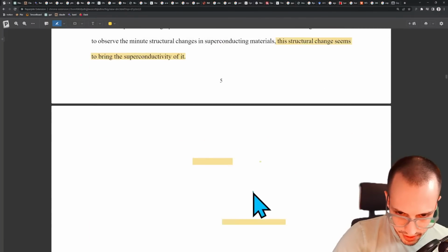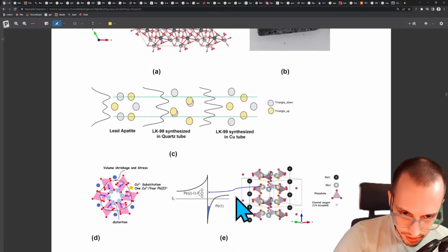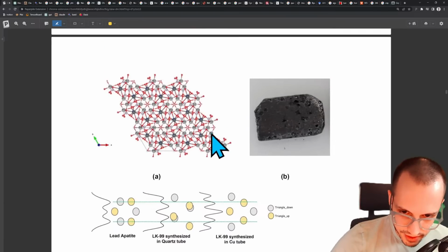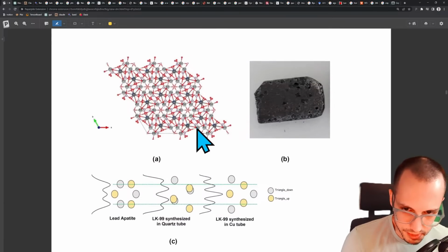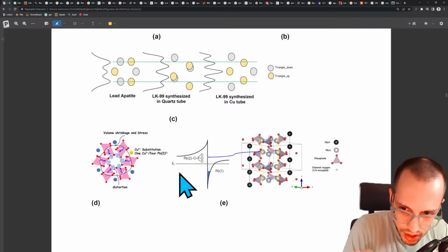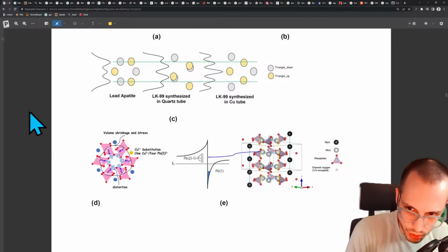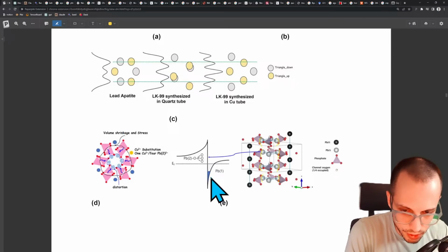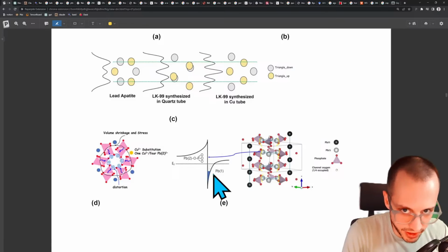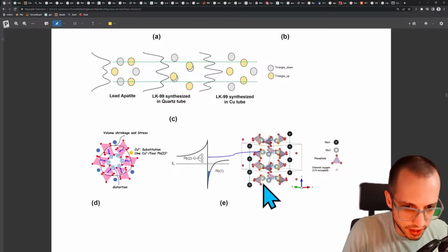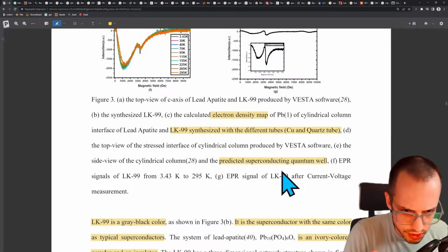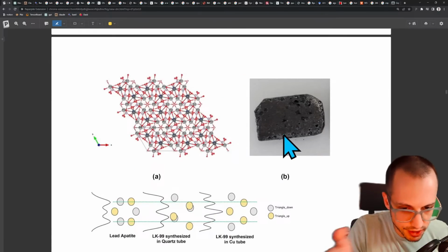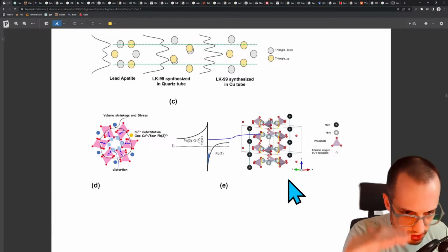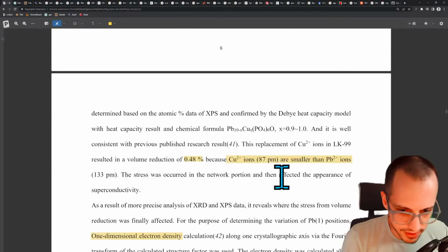The way that they do it is by replacing one of the lead ions in this crystalline structure with a copper ion. This crystalline structure of lead apatite is kind of jam-packed, and by putting the little copper in there, you pack it even more, and you get this distortion, or volume shrinkage, that leads to a superconducting quantum well. That superconducting quantum well has basically zero resistance, so electrons can travel through it freely. Apparently they also tunnel between the different wells. The metal is going to have a bunch of these superconducting quantum wells, aligned with the z-axis of this crystal structure. And yeah, that's basically it.